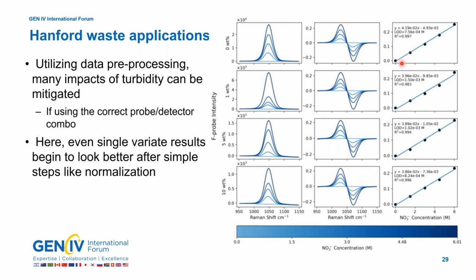And the last slide shows the signal strength as a function of nitrate concentration. The x-axis here is nitrate concentration. And from 0 all the way up to 10 weight percent, we have essentially the same sensitivity of scale. Again, that's because we can do the pre-processing step of first derivative, and also we do some normalization using that water hydroxide band to normalize our spectra. I just want to point out the slope of these lines is about 4 times 10 to the minus 2 for each one of these applications, from 0 to 10 weight percent solids, meaning the sensitivity of this measurement has not been degraded by increasing to high weight percent solids. So the combination of probe design and pre-processing steps really does a really good job.